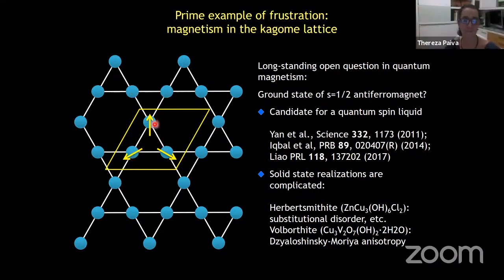Yeah. And that combination of sites, as you know, creates also a flat band, but now in the middle of the band structure. And in fact, you can smoothly modulate. You can, for example, get to a setting where this bond has a positive kinetic energy, as does this one, but this one has a negative kinetic energy. We can make such a situation. And when that happens, actually you get back to the Kagome band structure, but it's flipped upside down.